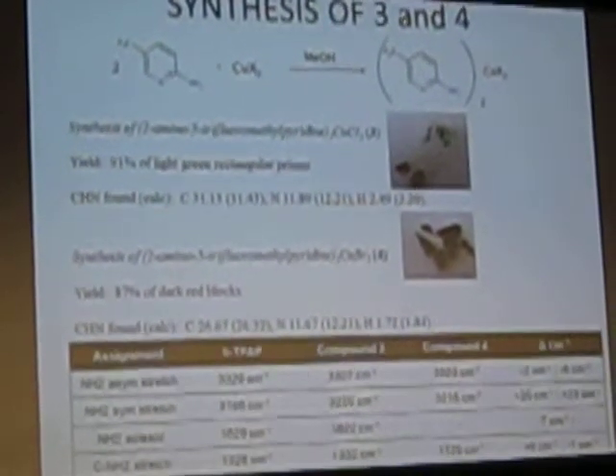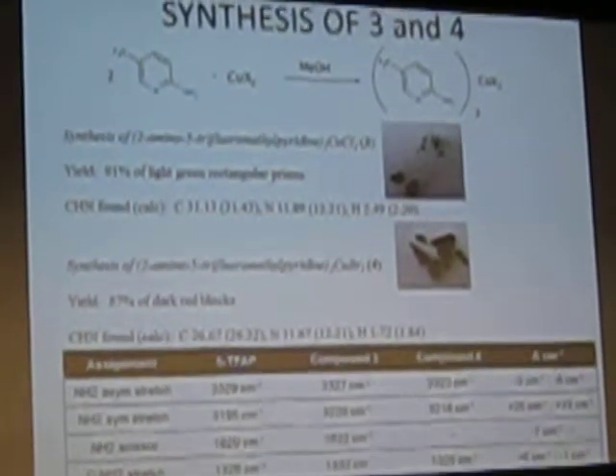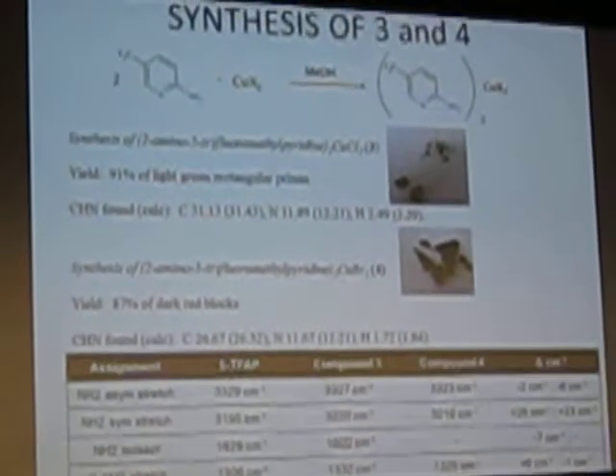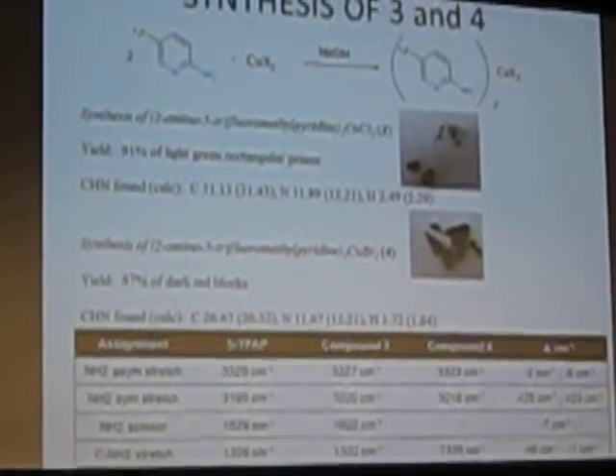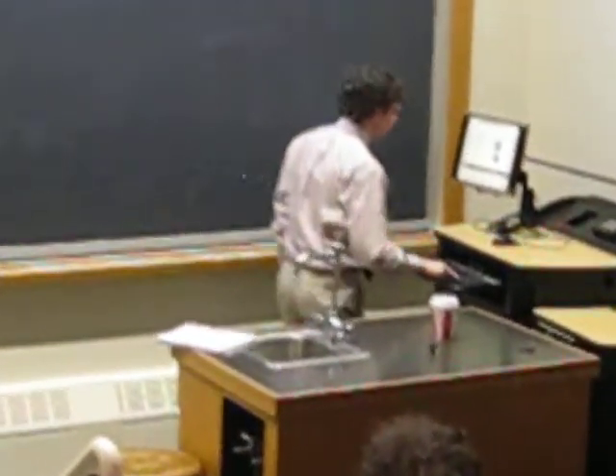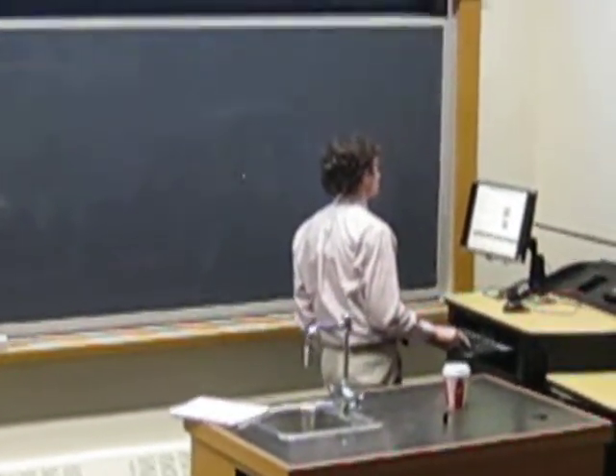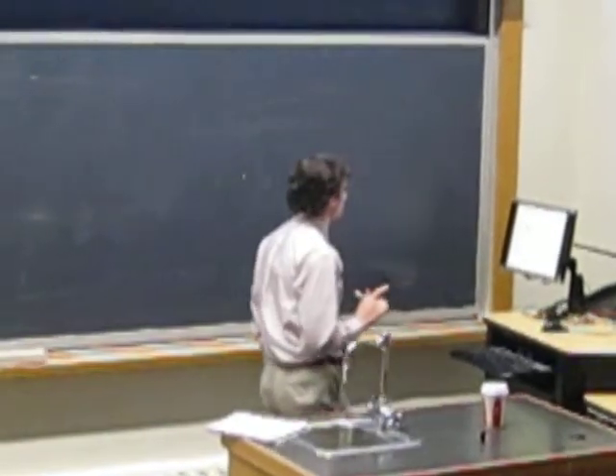There are very odd things going on in the IR. A full interpretation of the IR hasn't really been done yet, but there's a shift in the NH2 symmetrical stretch of about 25 reciprocal centimeters. And this is a rather bizarre shift, and I'm not really entirely sure why that's going on. But everything else agrees with at least the starting material. You don't change the starting material too much when you coordinate the copper to the pyridine ring. Or at least that's the theory.